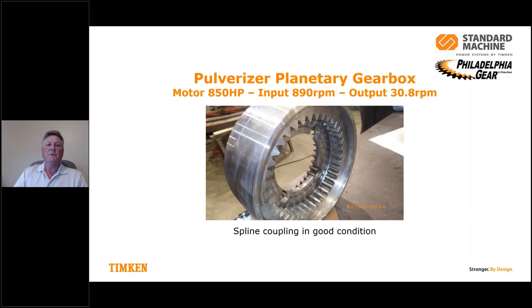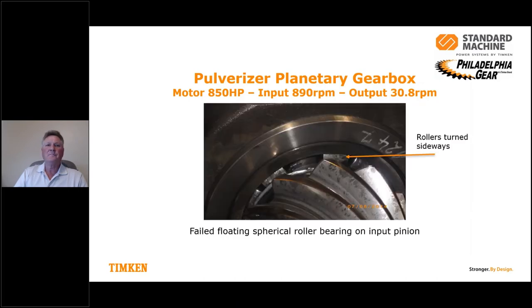The spline coupling was in remarkably good condition. So we looked at the bearings down on the lower section of the gearbox, and you could see that they were actually turned sideways, so the cage failed and the rollers packed up. It was very evident there was a problem there.